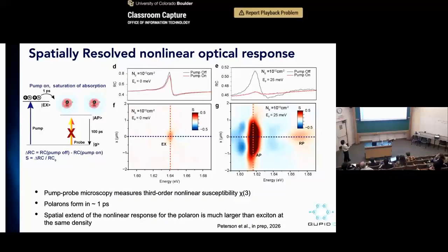For the polaron, what you see is that at the same injection density, about 10 to the 12, for the bare exciton you barely change the reflectance spectrum. But in the polaron, you almost 100% quench that transition. This is because once you create an excitation, this polaron, and they're large, you can no longer put another polaron in the same space. This indicates that the interaction length scale is much larger than for the exciton alone. We can also spatially image it. For the exciton, the nonlinear response is restricted to the area where you pump it, but for the polaron, it's much more extended, over a few microns. So I don't have much time.